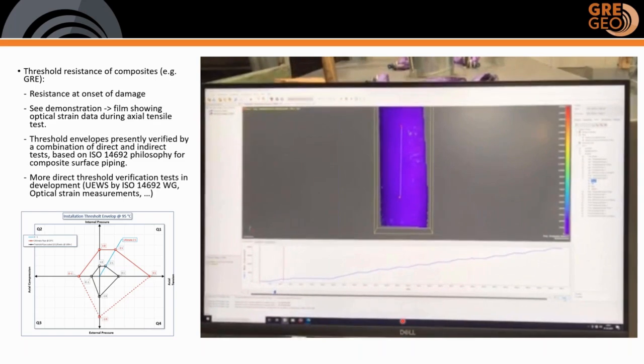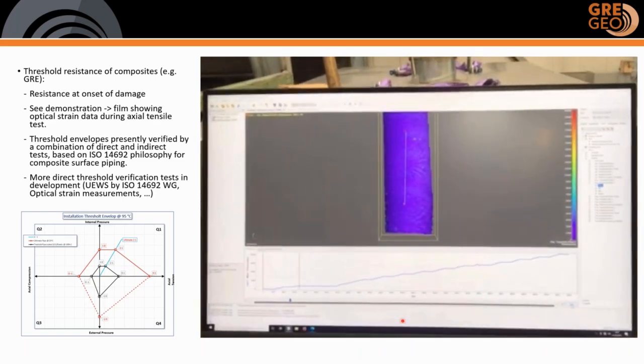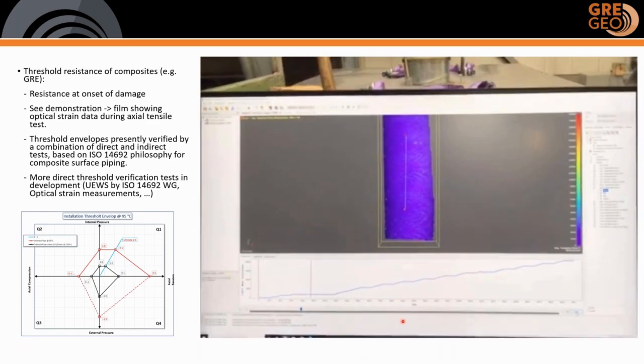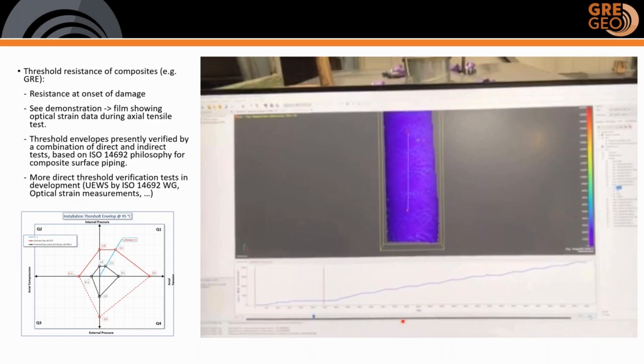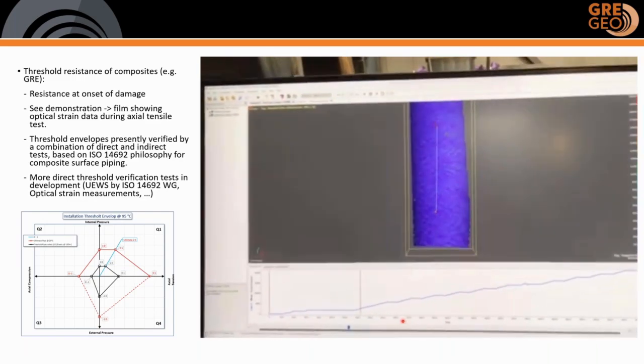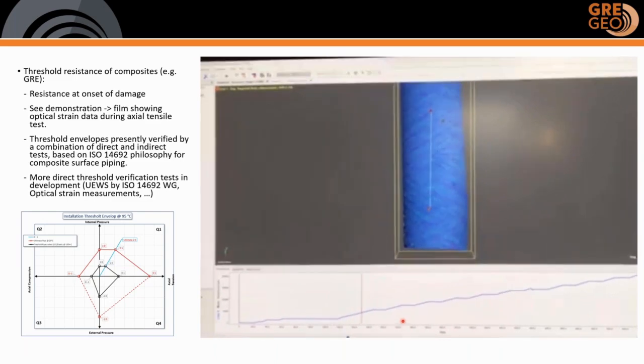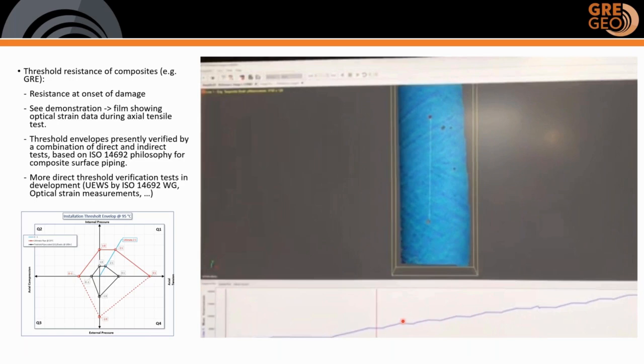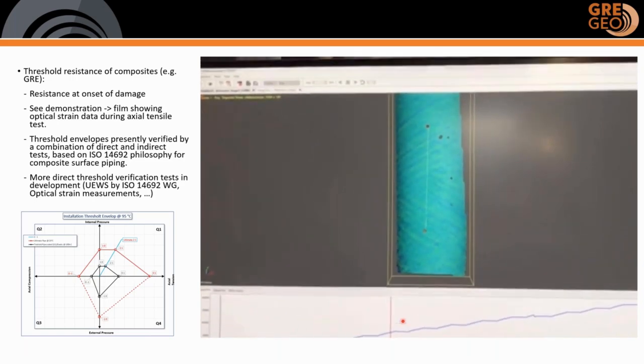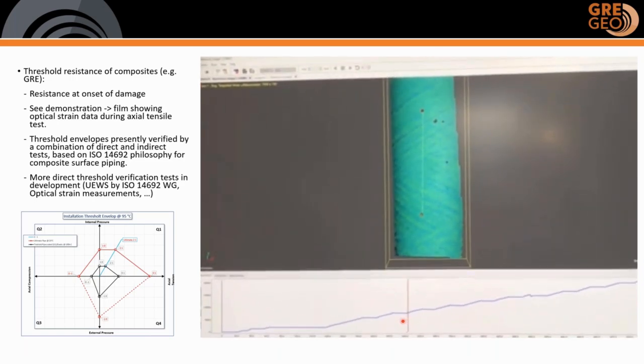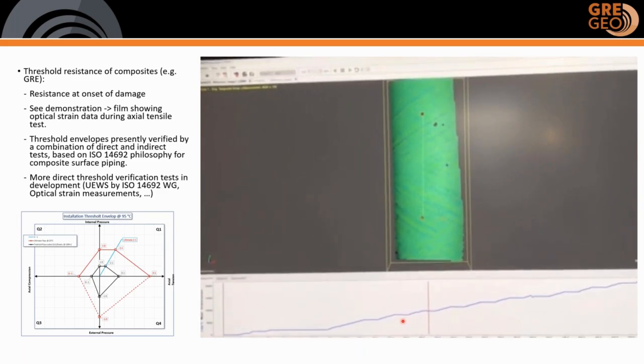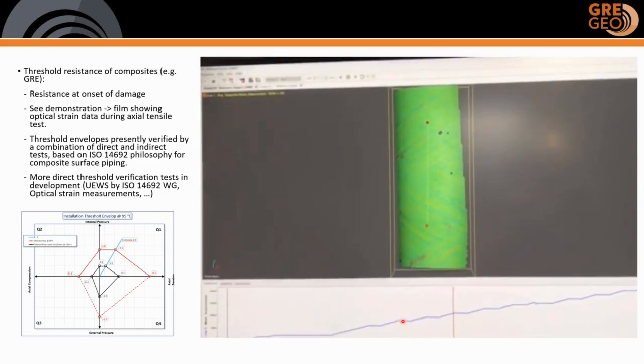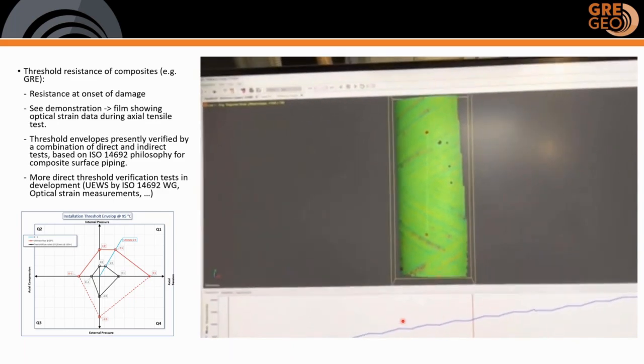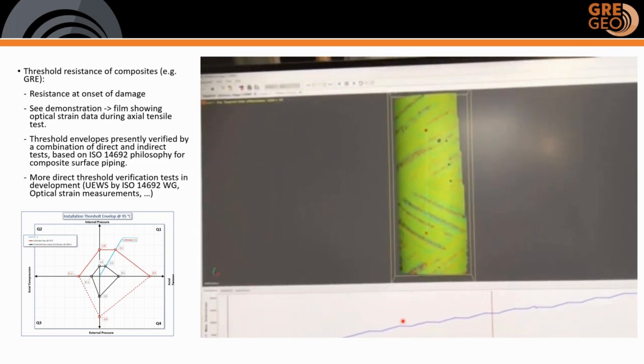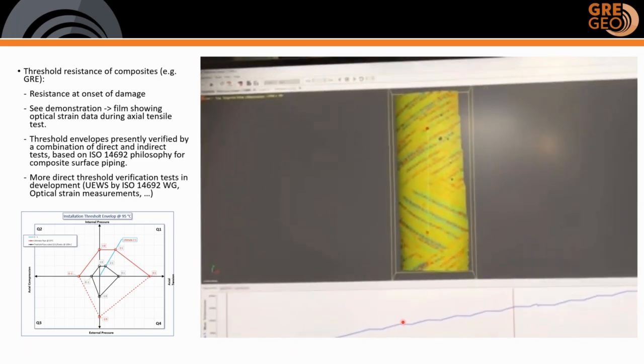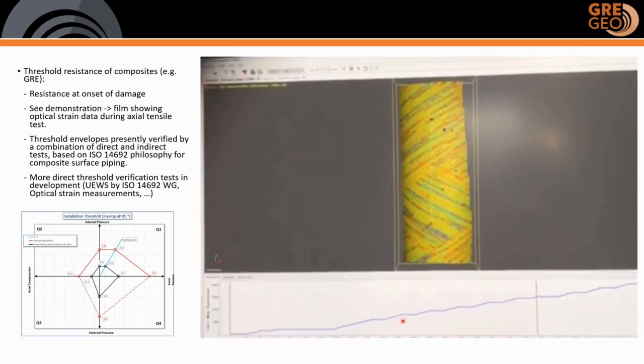So what you see here is the optical strain measurement to detect the onset of the crack development. In this particular case, the strain was measured over a length of 7 millimeters. That's indicated by the line you see drawn on the pipe. And the standard deviation of the strain was plotted against the pressure and shows a linear development, as you see in the plot below. At the onset of the crack development, the line deviates from linearity, and that could be used as a threshold value. And this point was found to correlate well with classical laminate theory and failure criteria used.